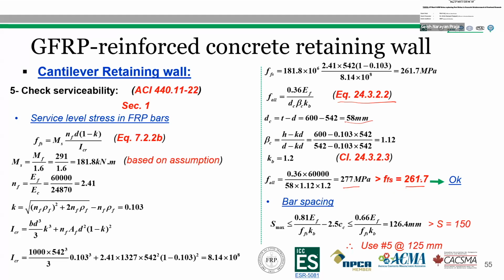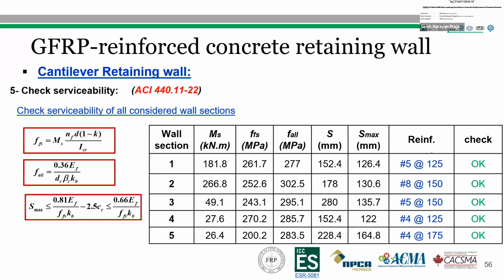So we also need to calculate the bar spacing using these two equations, and we found that the bar spacing is less than what we provided. We provided 150 millimeter, but for the serviceability requirement, the requirement is 126.4 millimeter. So we will reduce our spacing to 125 millimeter. So following the similar process, we'll check the serviceability for the rest of the sections.